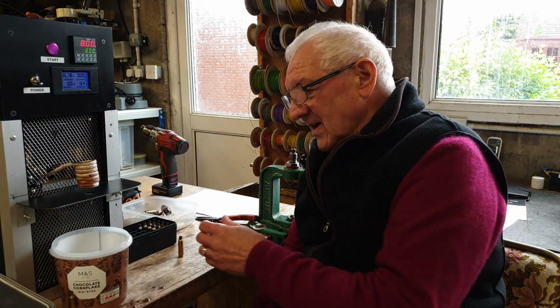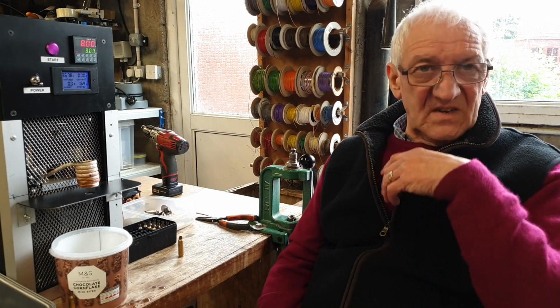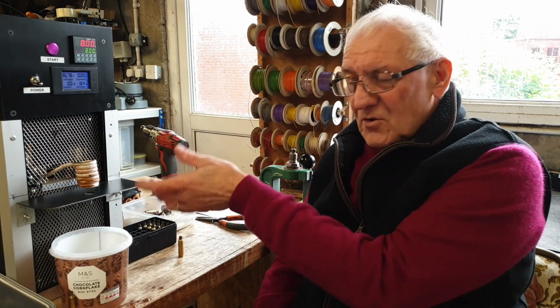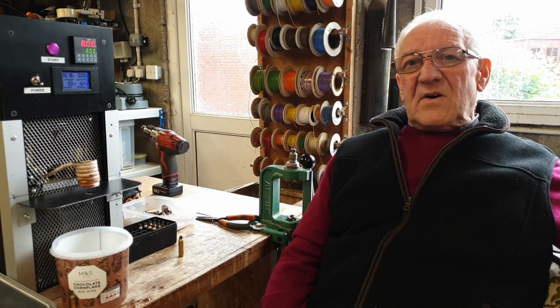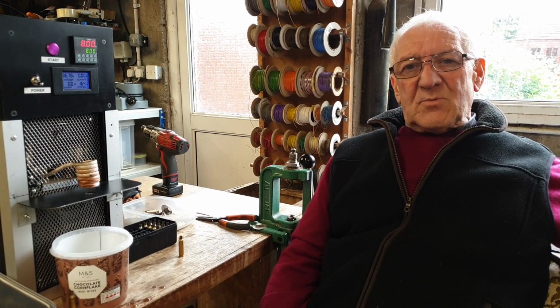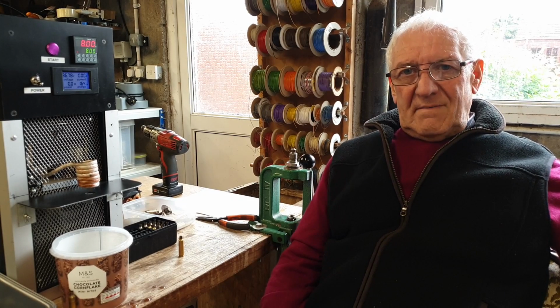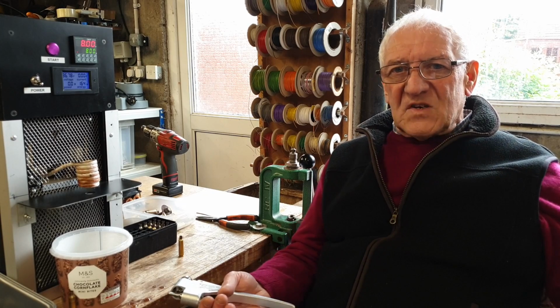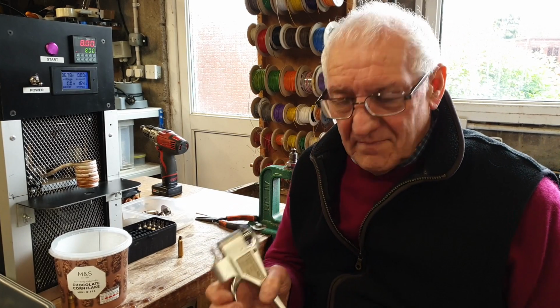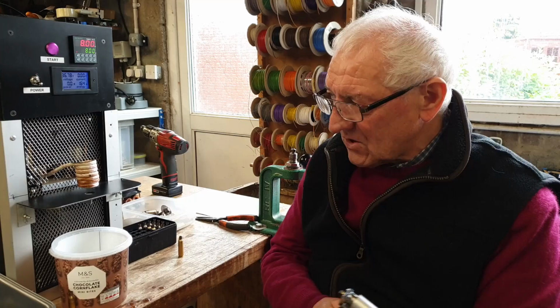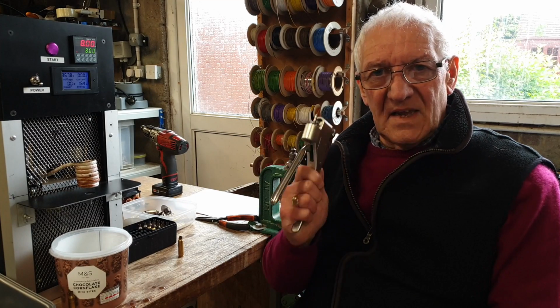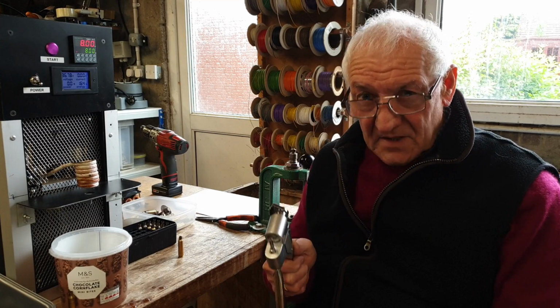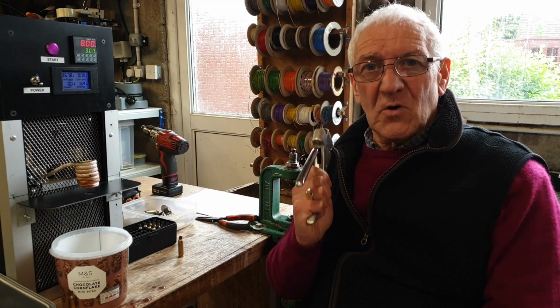So I think I've just proved fairly clearly that the brass started out hard, 17, 18. We've annealed it and we've brought it back to the same value as my brand new brass, which has been tested by the laboratory. So I think that validates the method. So I'm now confident that I can take brass and anneal it and be confident that it is properly annealed.